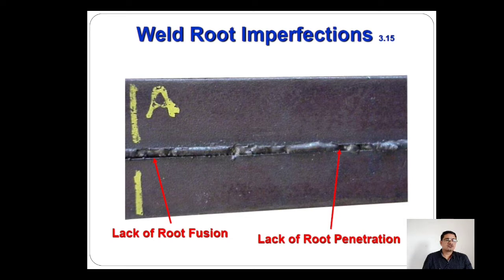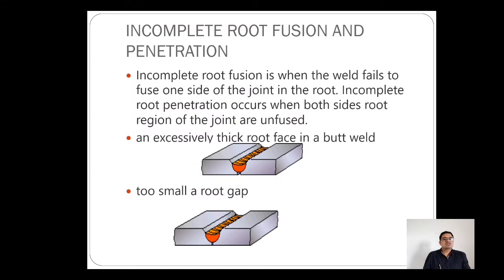So in lack of root penetration, what will happen when the welder is performing the welding? The welding bead does not properly penetrate the back side of the plate, or you can say the root side of the plate. So in this, friends, you can see certain reasons for this kind of defect. Number one reason may be the excessive thick root face in the butt weld.